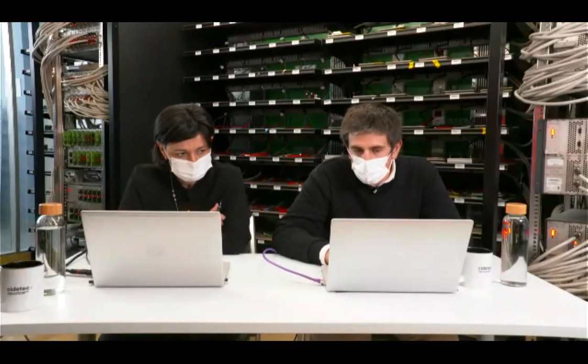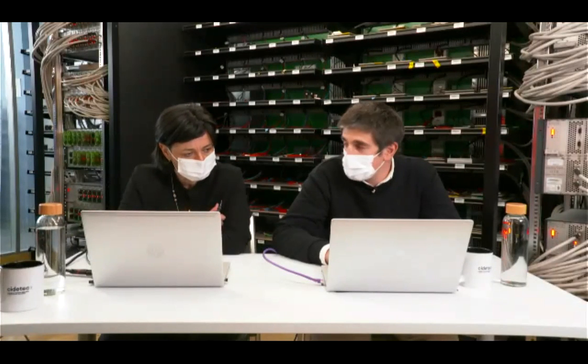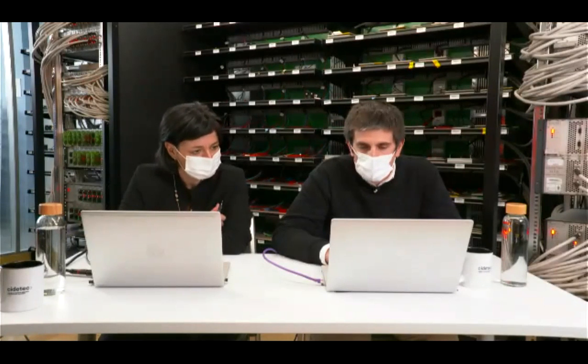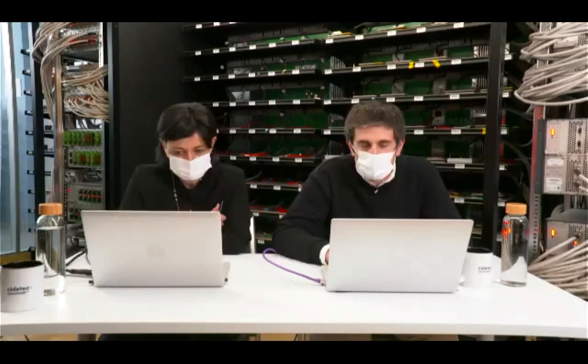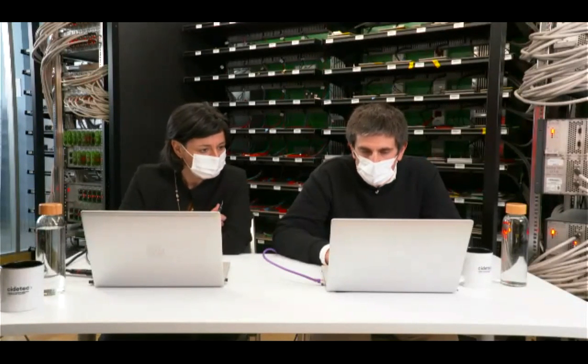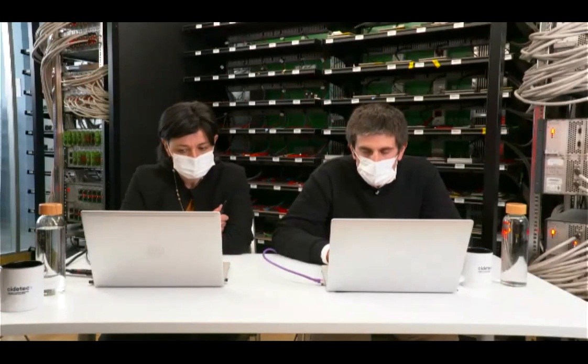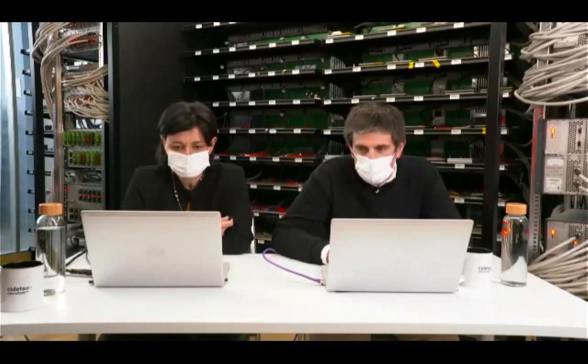So also there are questions regarding the drying temperature. I guess that they are asking about the drying temperature of the stack. We have to see that the main problematic part of this drying is the separator, because once you are doing the drying, the separator is the material that is melting before the rest. And you have to be sure that you are not changing the chemistry and the parameters of the separator.